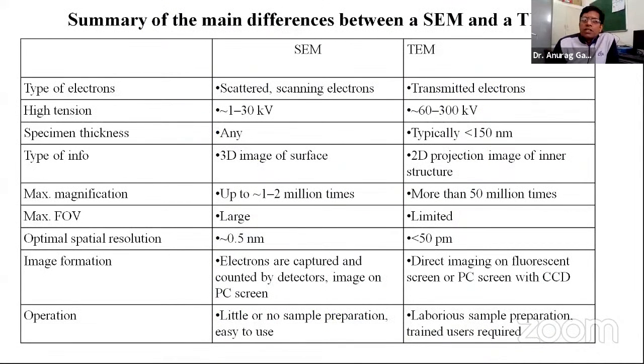So this is the summary of the main differences between scanning electron microscopy and transmission electron microscopy. The type of electrons: in scanning we use scattered electrons, in transmission electron microscopy we use the transmitted electrons. Then how much voltage you apply at the anode. In SEM it is 1 to 30 kilovolt, but in TEM 60 to 300 kilovolt. So naturally we are applying high voltage in TEM. Why? Because the electron beam must be transmitted, so it should be highly energetic. So voltage must be high.